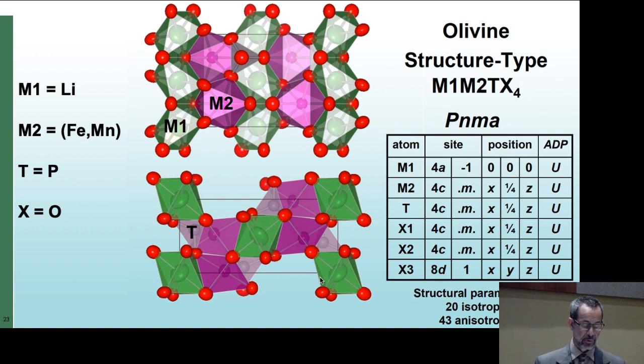Triphylite-lithiophilite has the olivine structure type. The iron and manganese are randomly distributed on the M2 site, and lithium is on this other octahedral site, forming octahedral chains.